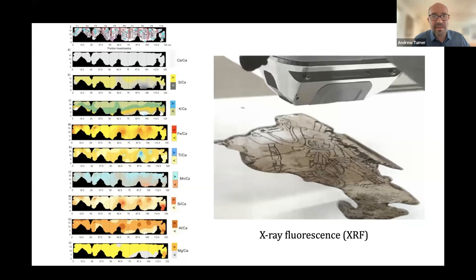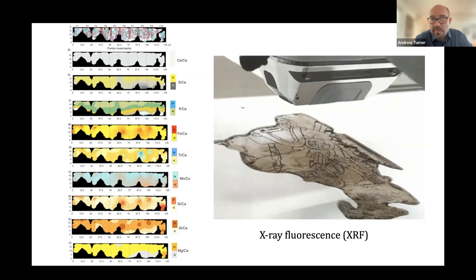Some really interesting things came to light. The paper itself was made out of the inner bark of a fig tree with no signs of crushing — basically thin layers of inner bark, three plies laid with alternating grain pattern to give the book more tensile strength. There were two types of red: iron ore hematite and cochineal, derived from an insect that feeds on nopal cactus. The Maya Blue was confirmed as palygorskite clay. It had been munched on by insects consistent with those found in a cave or burial. So basically everything pointed to this being an authentic manuscript.